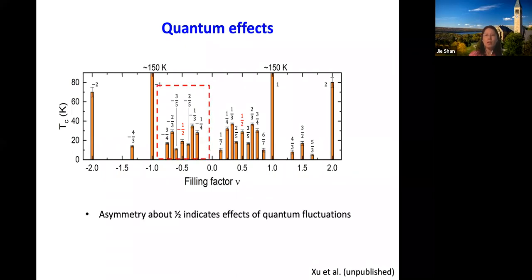One simple thing to look at is this nu equals one half. You can think of this as either a half filled lattice or a half empty lattice. So filled and empty are symmetric, so they are equivalent. If the kinetic energy or quantum fluctuations are not important, then we expect 1/3 and 2/3 to be identical, 1/4 and 3/4 to be identical, and so on. But we see that they are not quite identical, especially on the hole doping side, and that tells us that the quantum fluctuations are important, especially for the hole side.